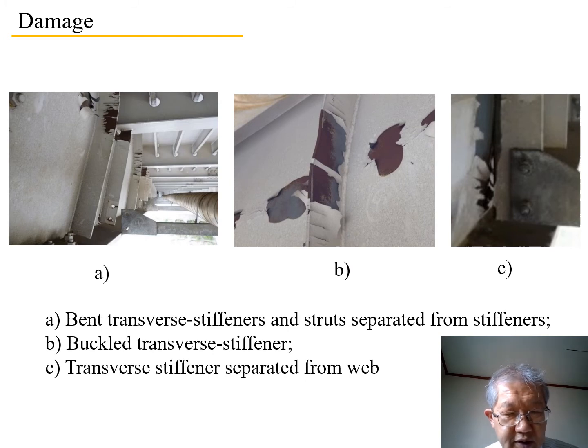The deformation is not the only damage caused by the collision. There are some other damages shown in these photos. This shows the bent transverse stiffeners like this, and the struts were separated from stiffeners like this. There were bolts, but they had gone. And this is the buckled transverse stiffeners here. And then we observed some transverse stiffeners were separated from the web because the welding was fractured. But fortunately, there was no damage around bearings and no cracks in the main girder. So the major concern was the deformation of the girder.